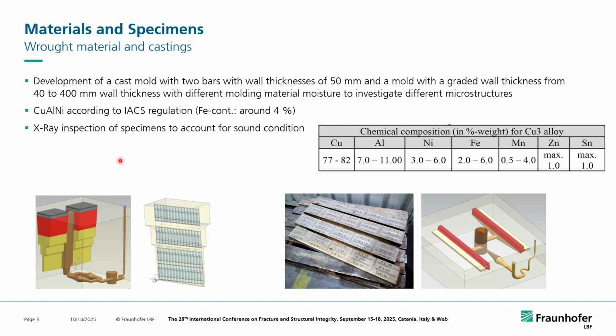After the specimen removal, all those specimens were X-ray examined to account for sound condition. So we didn't want to test in the first step, especially from those bars, specimens that might have a larger fraction of shrinkages, at least those that will be deemed unsound and defective when they are detected in a ship propeller later on in the serial production. There are different sizes that are definitely not accepted, and so we wanted to prevent those bars and specimens from having those critical levels of shrinkages.